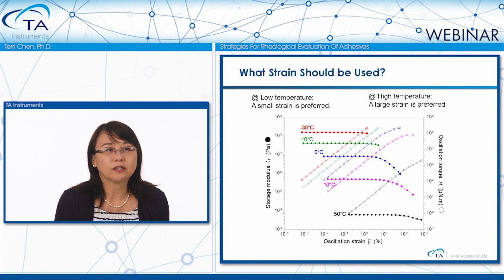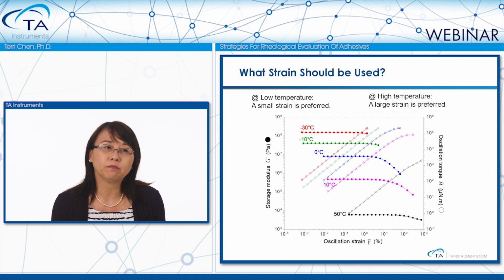Also, below glass transition, the sample is fragile. Using a large strain may crack the sample. Therefore, at low measurement temperature, using a smaller strain is preferred.